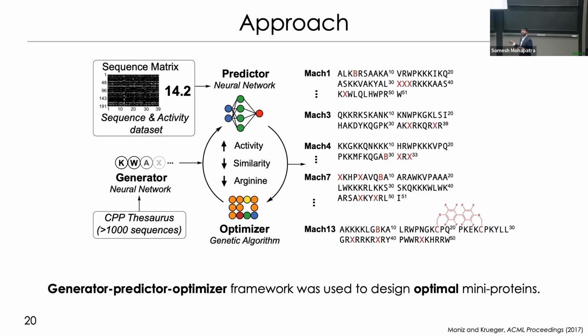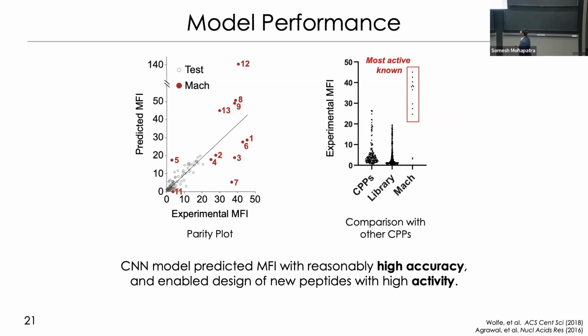And these 13 peptides, or the MAC peptides, were carried forward to be tested experimentally in vitro in cells. And subsequently, some of these were selected to be tested in vivo as well. So here are the results of the model. On the held out test dataset in the machine learning framework, which was essentially not shown to the model when it was trained, we had reasonable predictions, with an RMSE, or root mean square error, of 0.41 of the standard deviation of the training data. And for the MAC peptides, the model was decent enough to go well beyond the maximum of the training data and predict sequences which had activity as high as 50 in some cases.